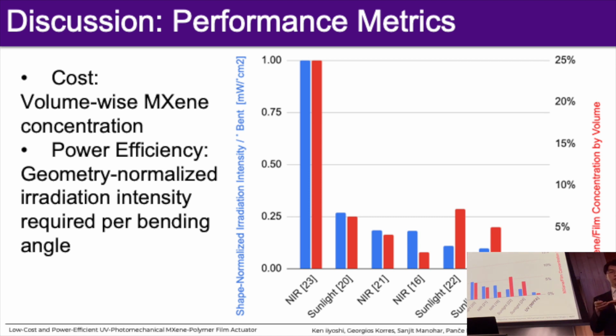For example, if it's a long film, we took that into account. And the result is that our film goes right around here. So it looks pretty nice as long as we keep the concentration quite low. And the research that we've shown before are somewhere around in this range. So not bad for a preliminary result.